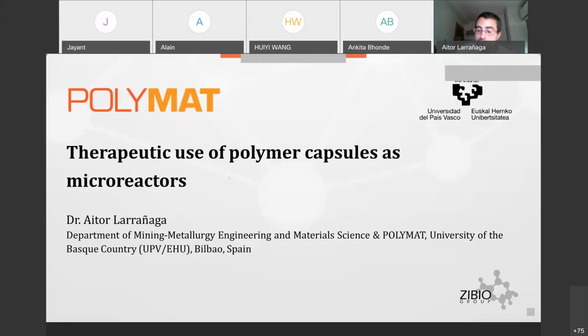And in terms of the size, well, the largest particle that I have ever made was 3 to 4 microns with calcium carbonate microparticles, but I don't see any problem to do slightly bigger particles by using other kinds of templates. Of course, in this case, you could go for polystyrene microparticles that are commercially available. So I usually see the problem when you try to go to smaller particles.